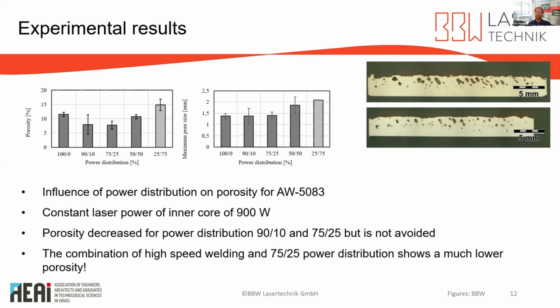The maximum pore size is displayed in the middle figure for different power distributions. Maximum pore size is very similar for power distributions 100 to 0 to 75 to 25%. It increases with further power fraction into the outer ring. This is maybe because of the larger vapor capillary. Larger bulges exist at the bottom of the capillary, which could lead to larger pores.